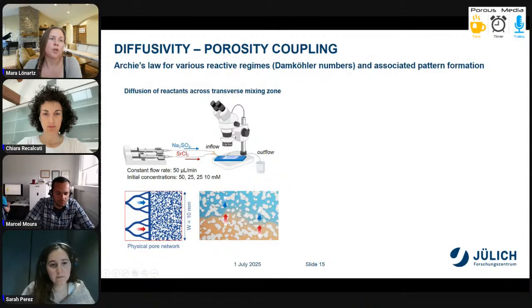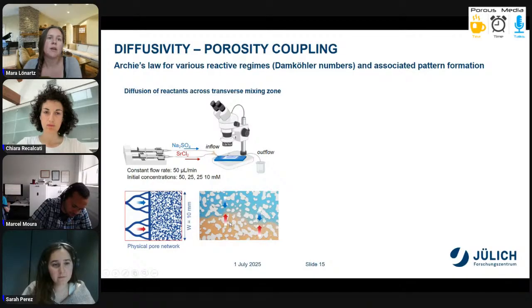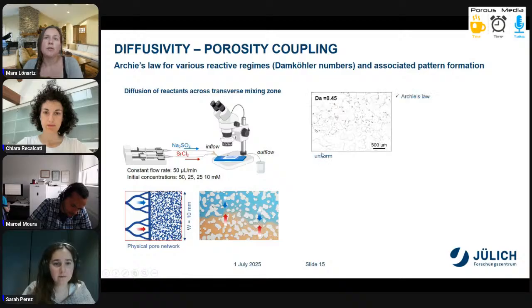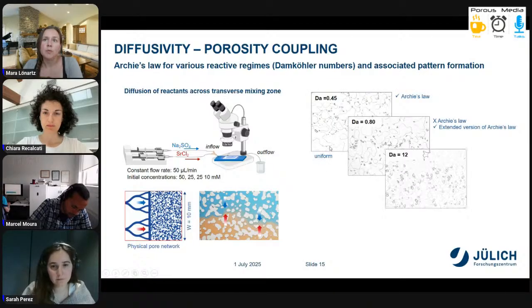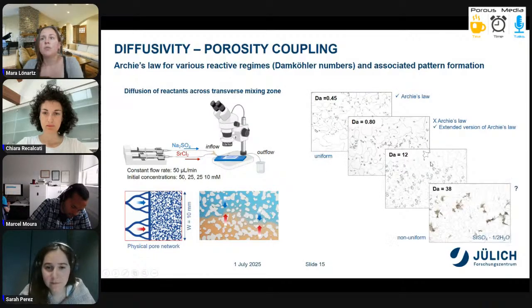resembles a realistic pore geometry, and we injected, again, sodium sulfate and strontium chloride from one side at a very high flow rate to create such a sharp interface, so that we have diffusion across this interface from different initial concentrations. And what we could see here is that with increasing Damköhler number, the distribution of celestine crystals was getting